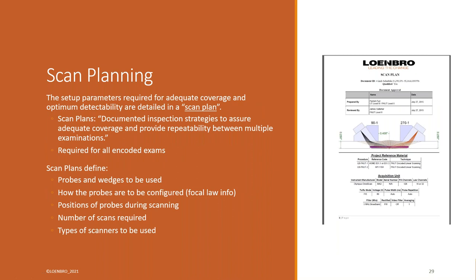All right, so those are the two basic scan types. There's others, but we don't want to get too deep into this. Scan planning is a term we use in phased-array that if you plan on using it or are using it, if it's an encoded evaluation or they're storing data or code work, there should be a scan plan associated with that particular inspection. By ASME, American Society of Mechanical Engineers, for those that might not be familiar, their definition of a scan plan is a documented inspection strategy to assure adequate coverage and to provide repeatability between multiple or subsequent examinations. In other words, if you had a bunch of 4-inch Schedule 80 pipe to shoot, you wouldn't want one guy doing it different than another guy, and you wouldn't want to do it different on Monday than you did it on Friday. If you want to find a good way to do it, you want to be able to repeat that for subsequent examinations. The scan plan should define everything that the operator needs to be able to set it up, evaluate, collect the data, so how many scans, where the probes need to be, so on and so forth.